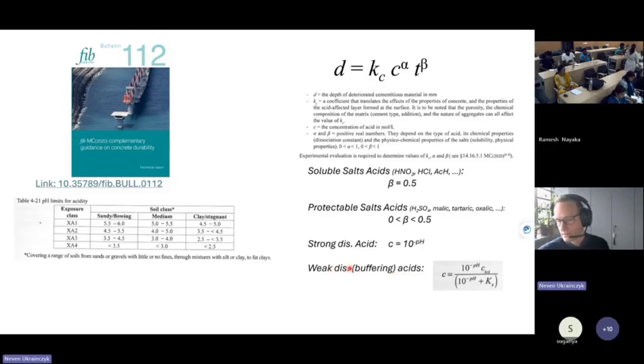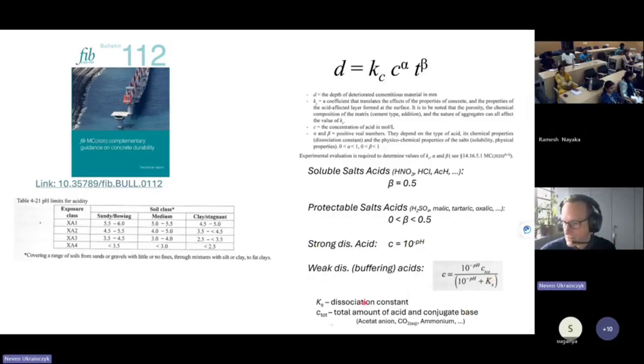So it's not weak. It can even destroy more concrete than the strong one for the same pH, because you have this buffering effect. Weak means only that it's a weakly dissociated acid, and this is a strongly dissociated acid like sulfuric acid, and this would be an example of acetic acid, so the vinegar. So the Ks is the dissociation constant, that's the equilibrium constant basically, which you know now very well from chemistry. And the C total is the total amount of acid, because if it's partially dissociated, then the total amount is what is important.